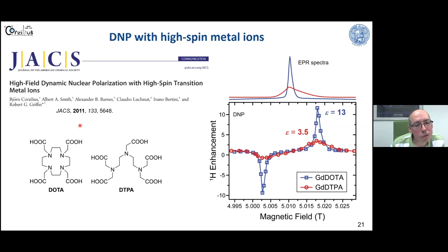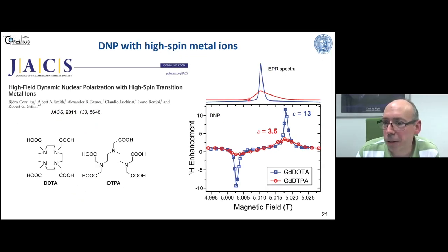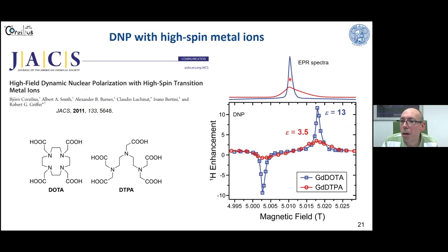We can also see that depending on their zero field splitting, DOTA has a much, much smaller zero field splitting as compared to DTPA. You can see this here on the breadth practically of the EPR spectra. So DOTA gives you a much, much more narrow central transition compared to DTPA. And this is also reflected pretty one-to-one in the DNP field profiles.